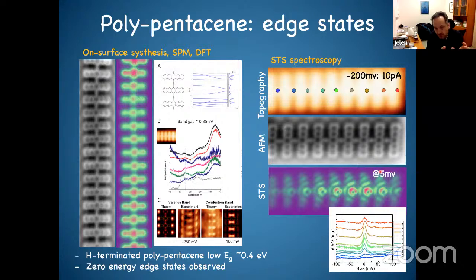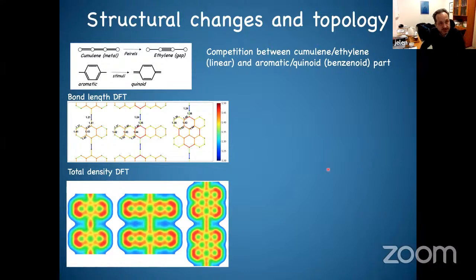But going back, if you remember, I told you this is also somehow related to the change of the pi-conjugation. Because what I'm showing here is just the theoretical calculations, and we look at the bond length. If I look at these topologically trivial states, I see that the bond length of this triple bond is much shorter than in this topologically non-trivial state. So you see that it's not only how you terminate the electronic structure, but it's also reshuffling this simple double bond in some way. And if you look then at the total density calculated by DFT, this kind of triple bond which appears here has more accumulation of electronic density. Instead, when you elongate the bond, this accumulation starts to be more equal.